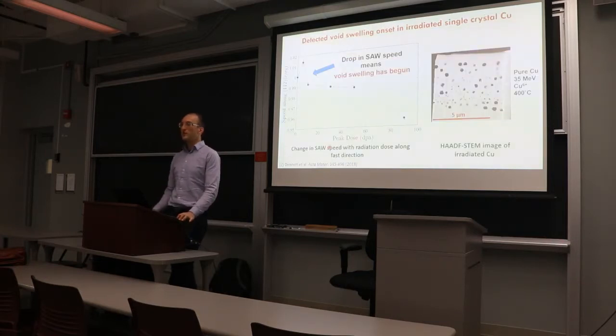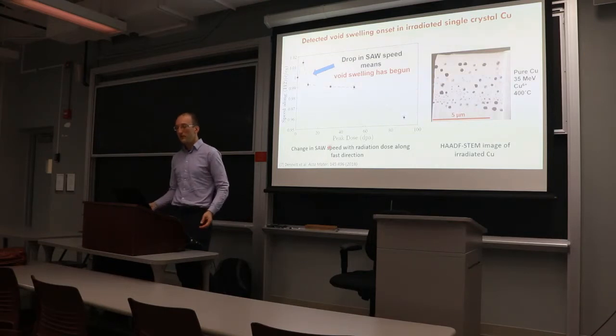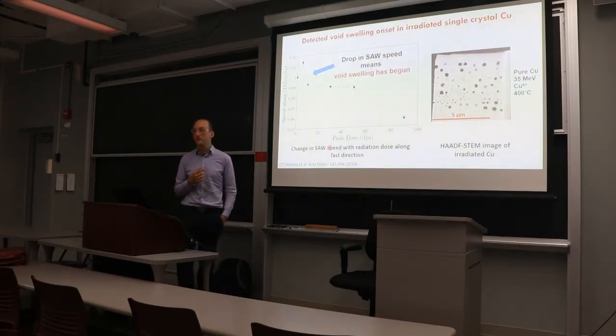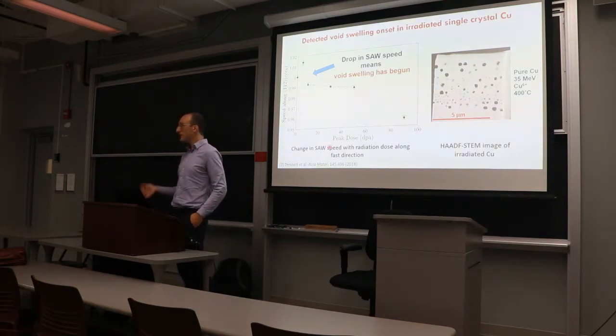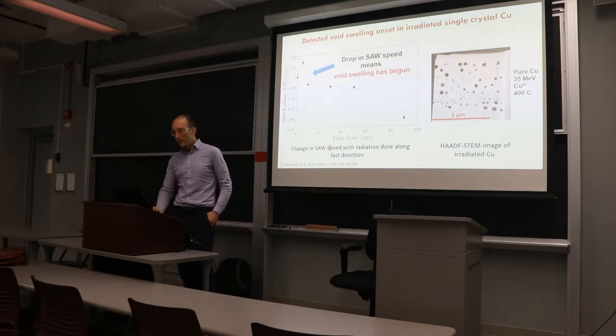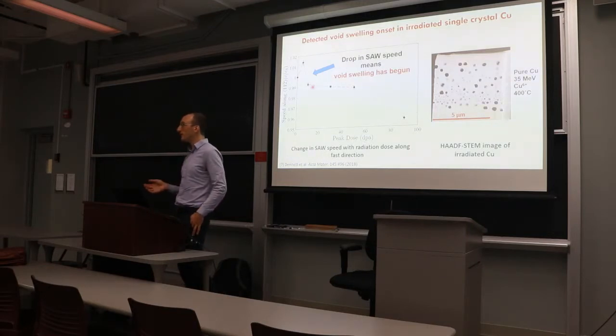We did a classical void swelling study of single crystal copper with copper irradiation. Made basically the same kind of graph as Dr. Gigax did for one material, but this took us half a year. We were able to show with our TGS technique and TEM backup that when the surface acoustic wave speed started to drop, that's when the voids started to show up. So we have an indicator for the onset of void swelling, but it still took forever, right? This graph took 6 months to make.